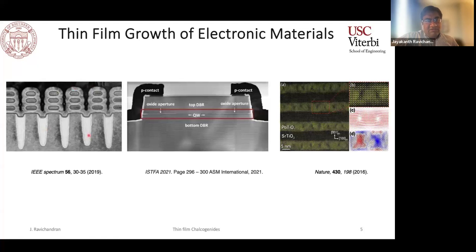This involves an interesting silicon germanium silicon heterostructure growth and then processing to get the surround gate structure. You also are seeing some of these light emission devices where you're creating quantum cascade lasers and so forth by leveraging the ability to grow III-V and atomically precise structures with well-defined compositions. On the right, something that should be extremely familiar to several in the audience, particularly, I think I saw Professor Chen had logged into the talk, the oxide heterostructures, where development of some of these polarization textures has been of interest in the oxide community in the last decade or so.